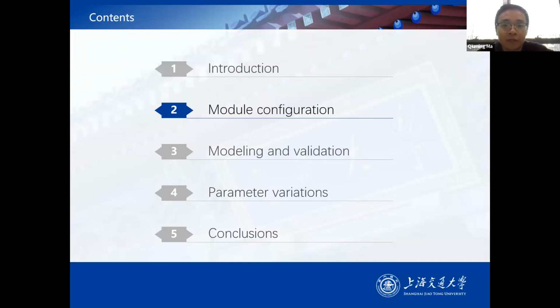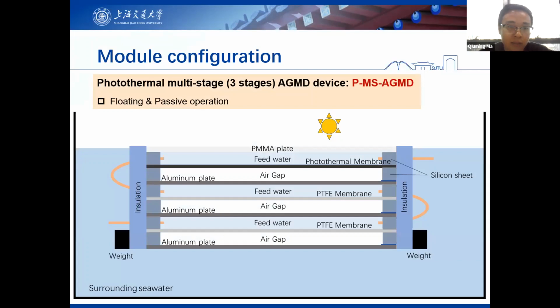And then the module configuration. We designed a photothermal multi-stage AGMD device as shown in the picture. It can be in passive operation and can be floating on the water surface. As you can see, there are 3 stages in our current design. The top stage membrane is the photothermal membrane, I'll introduce it later, and the bottom 2 stages are just normal membrane. All 3 feed layers are connected in series. And we use some weight to float the whole device just a little bit above the water surface.